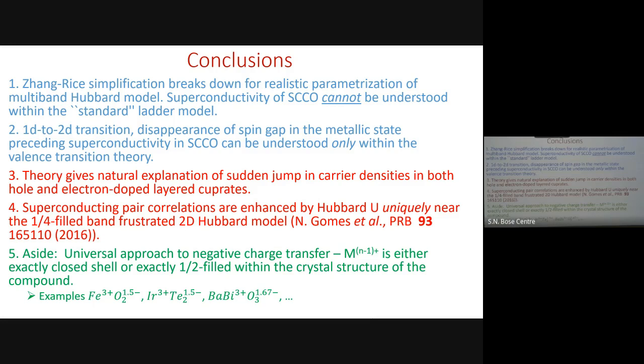In the electron doped materials, the transition from antiferromagnetic to superconductor occurs very subtly, and the NQR splitting disappears. I had to learn NQR to find this out. It's not in this paper. The splitting between the lines in NQR is related to something called the electric field gradient, which is related to the asymmetry of the electron distribution. It just disappears. Five lines become one line exactly at that transition. That means the copper shell has become spherically symmetric. There's only one way, I think, it becomes spherically symmetric.